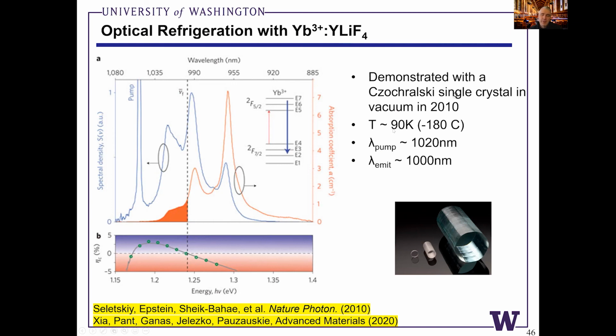They've recently published a paper showing you could cool the ceramic yttrium lithium fluoride doped with ytterbium ions to about 90 degrees Kelvin from room temperature. So this is getting close to where you could liquefy nitrogen. And typically for ytterbium, they pump at about, in the near infrared, about 1020 nanometers. The emission band is very broad, but it emits approximately 1000 nanometers.